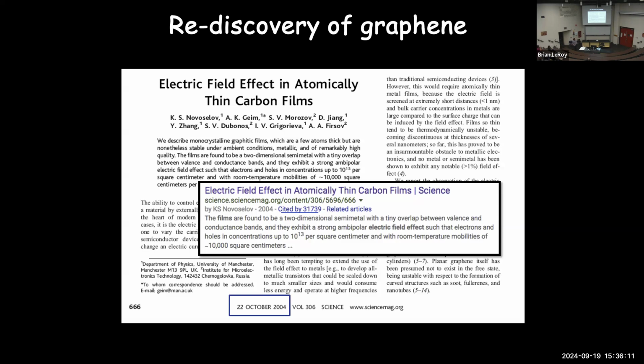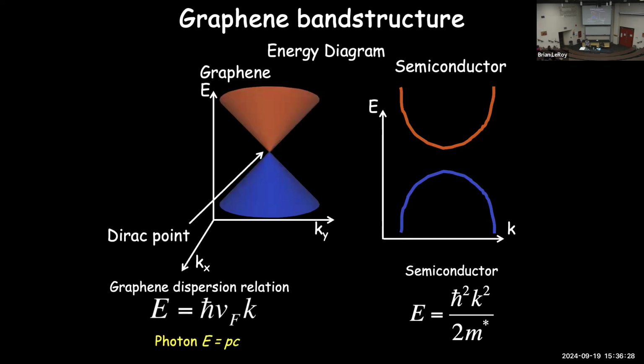What they were able to do here is to take this monolayer of material and put it on a boring substrate, in this case a silicon oxide substrate, which does not affect the electronic properties, and they could then access the interesting electronic properties of graphene. And in particular, what those interesting electronic properties that they were able to access is the dispersion relation, the energy versus momentum relation for the graphene.